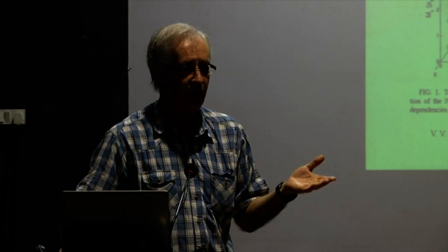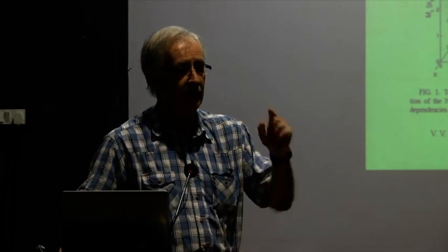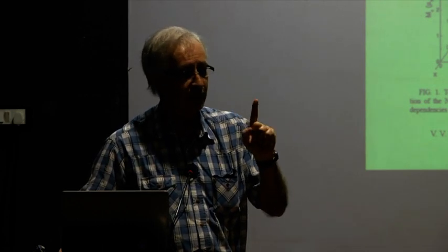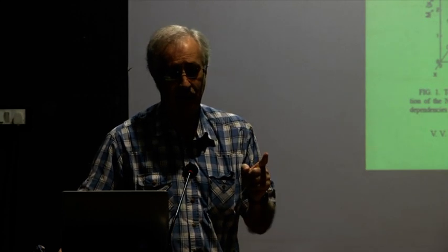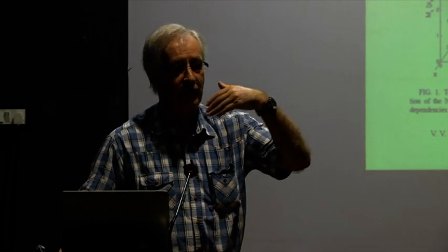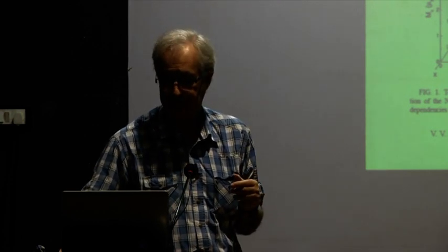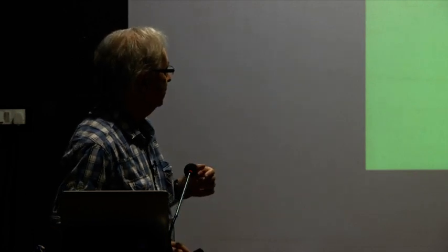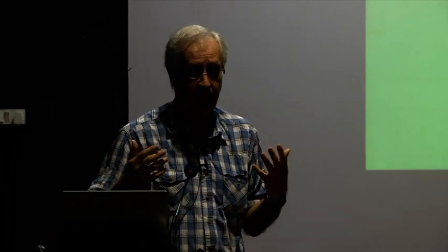Now, nickel, manganese, gallium, we said, yes, nickel 2, manganese, gallium. It's one of the very rare Heuslers that undergo martensitic transformation in the stoichiometric composition. That is nickel 50, manganese 25, gallium 25, okay? Normally, such Heuslers are all ferromagnetic and they're all in one phase. If you want to move around the Curie temperature, you can change the composition a little bit.